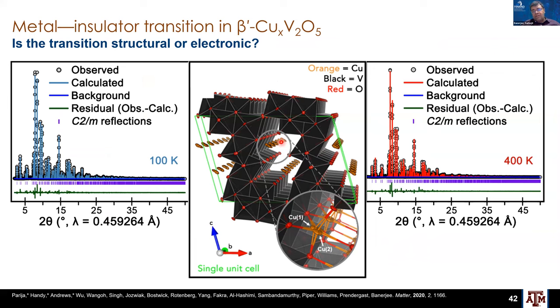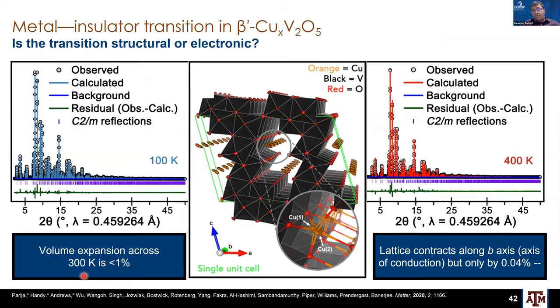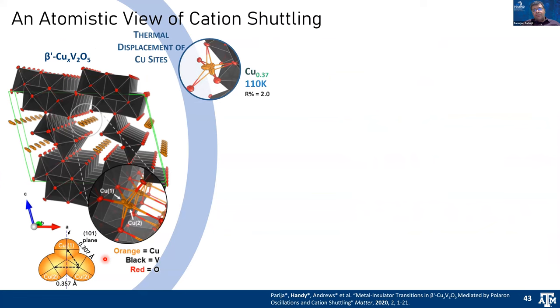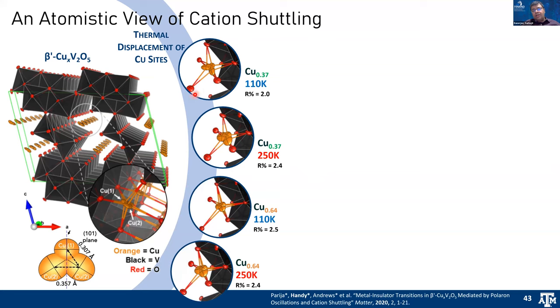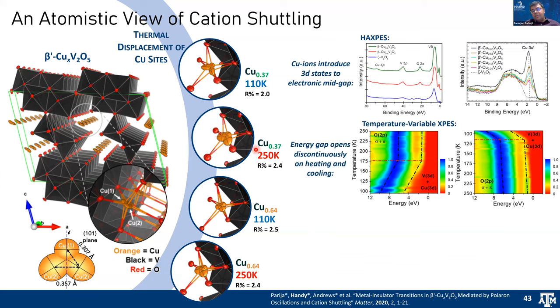This is the structure, copper inside the V2O5 tunnels. There's a very small volume expansion, so very low lattice involvement. And at 110 Kelvin, there's some split site disorder. Copper sits on one side, closer to one vanadium atom or another one. But at higher temperatures, copper starts to really be delocalized across these two sites. As a result, copper is plus one and the vanadium centers are reduced. And so when you've got this cation shuttling going on, you also have polarons oscillating on the V2O5 lattice.